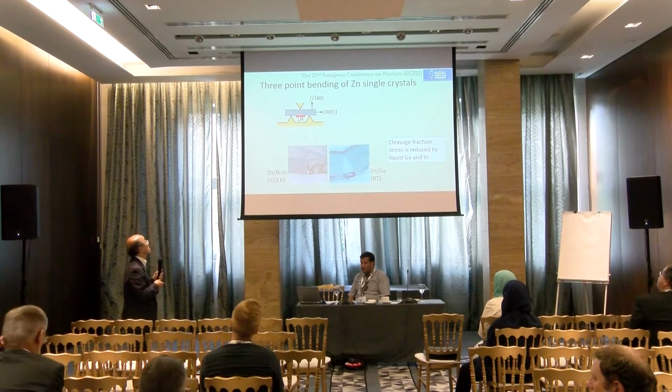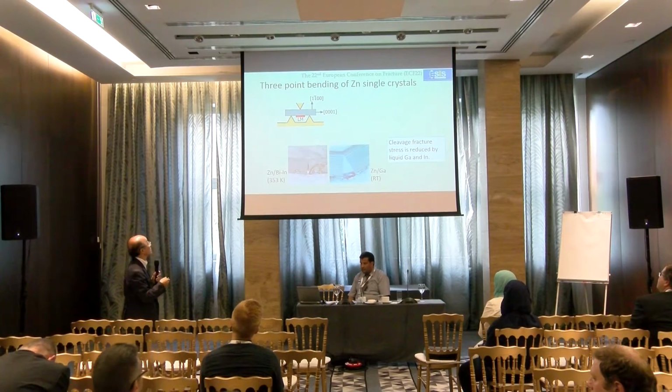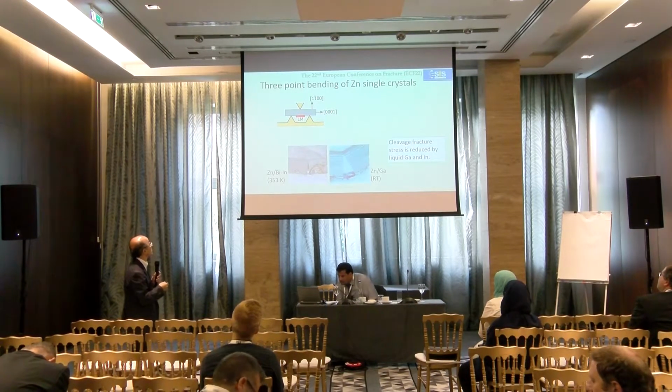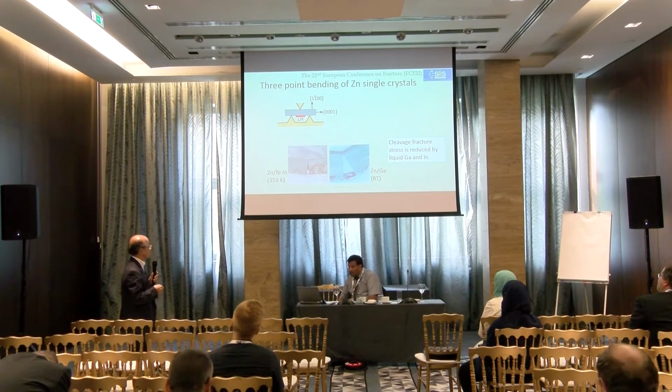We also made a 3-point bending test of zinc single crystal in this orientation. In the case of gallium and bismuth-indium, a crack on the basal plane is observed. So the cleavage fracture stress is reduced by these liquids.